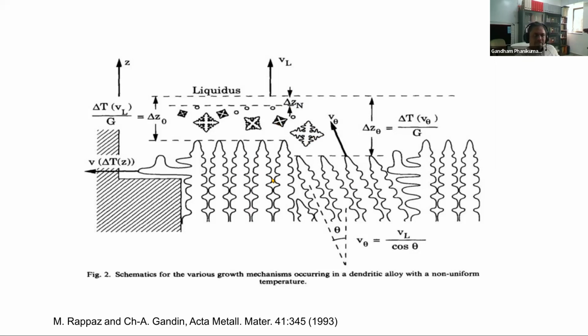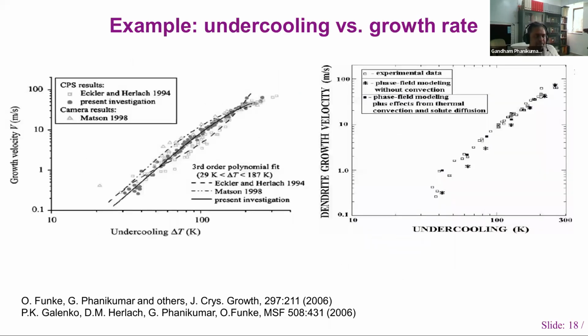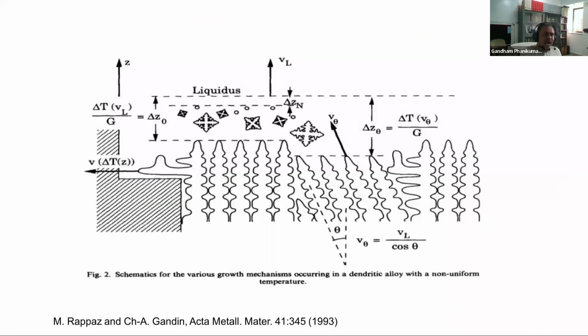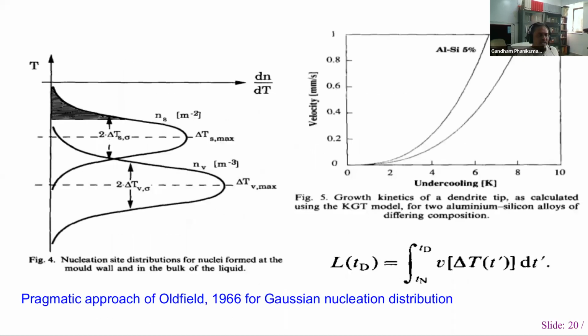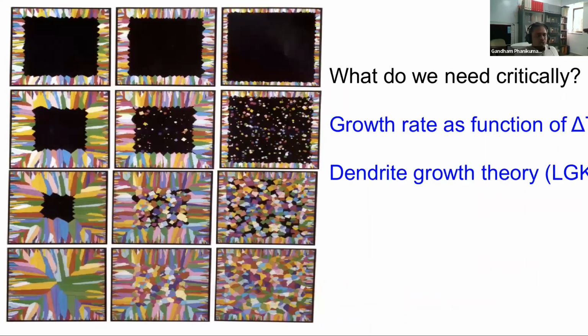And one important parameter for the competition is the velocity with which it can grow. Now that velocity is mapped with the undercooling in this manner. So this is basically coming as an outcome of the interface response function. So today there is a mathematical way of describing that, and that is available with us. And once you put that in, you can actually make some calibration of the number of nucleation events that can take place, and then start to simulate microstructure and the grain formation.